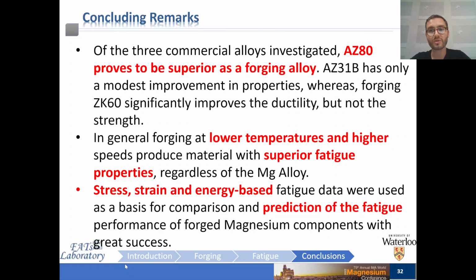In general, forging at lower temperatures and higher speeds produces material with superior fatigue properties, regardless of the magnesium alloy that's being investigated. Obviously, the specific alloy that you're looking at will have various levels of magnitude in which that statement is true. And finally, the stress, strain, and energy-based fatigue data that we looked at were used as a basis for comparison for predicting the fatigue performance of forged magnesium components, and this was done with great success. So we encourage you to employ these types of techniques, especially energy-based techniques, which work especially well for forged magnesium components, which is outlined in a number of journal publications that are referenced in this PowerPoint.